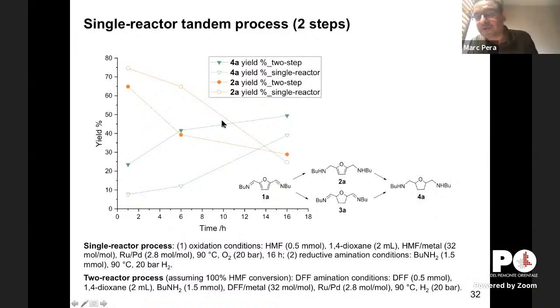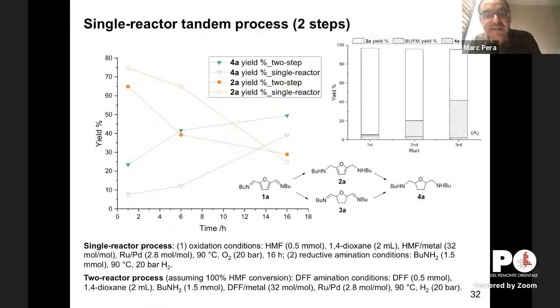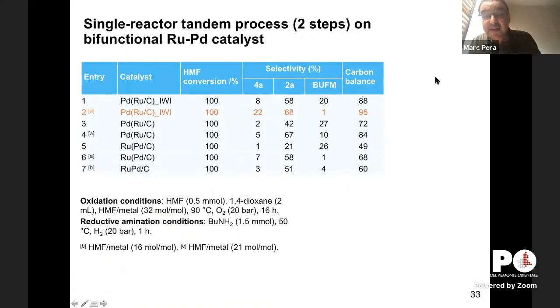You see that the system works quite well. And with these results, the stability is more or less decent. And what is very interesting from this result is that we could design a real bifunctional catalyst. That is a real milestone for this kind of processing. So in our case, we did something very simple as proof of concept.